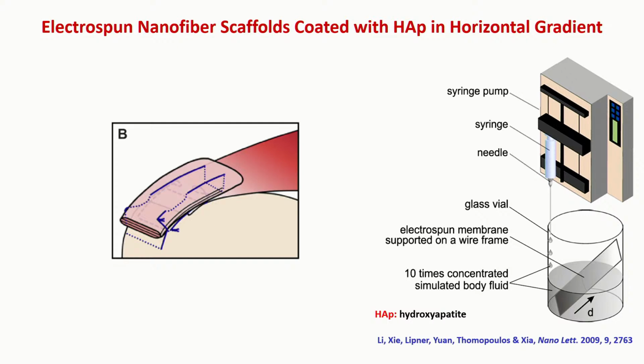And the idea is quite simple, as shown over here. You just take your scaffold, position it in this orientation, and then into this container you are going to add a solution. This is going to be 10 times concentrated simulated body fluid. It's a solution that's already highly concentrated in terms of mineral composition. So when you drop it into this container, there can be nucleation and growth on the surface of the scaffold. So you can have mineral being deposited onto this scaffold.